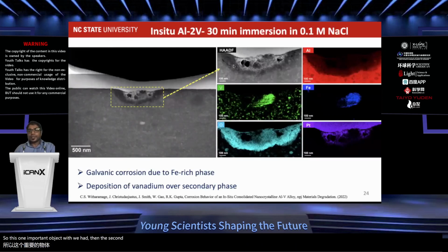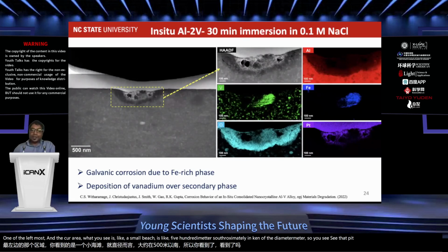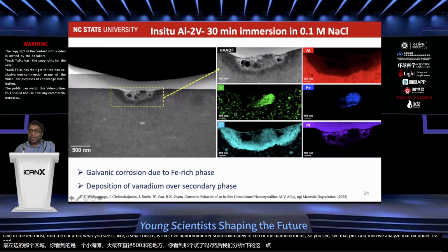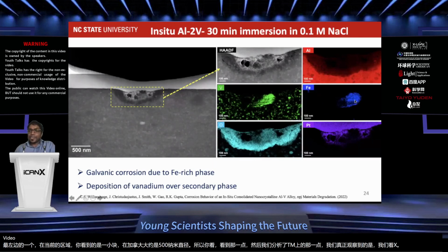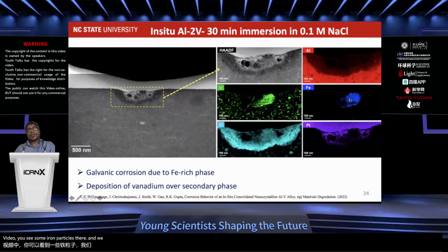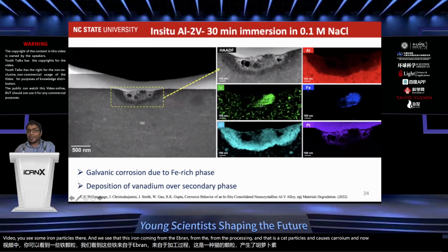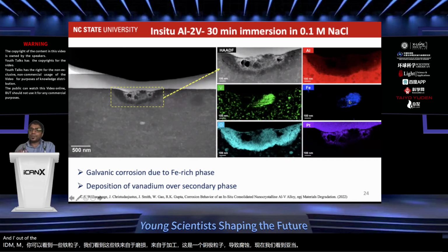Then the second image is a pretty important one, and this shows a pit. So you see this image here, right? The one on the leftmost, and the corroded area, what you see is a small pit. It's approximately 500 nanometers in diameter. So you see that pit, and then we analyzed that pit under TEM. And what we really observed was, we look at the EDX area maps. You see some iron particle there, and we see that this iron is coming from the abrasion, from the processing, and that is a cathodic particle and causes corrosion. And now we see that the vanadium and iron are in the same spot. Basically, vanadium is depositing on iron.